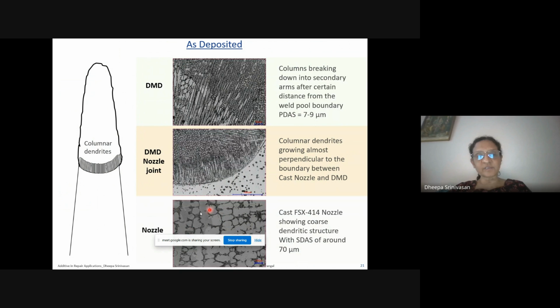What you could see here, the microstructure, this is the cast FSX414, and this is the additively manufactured powder based direct energy deposition. Except that here, as compared to the laser powder bed fusion, the columns are much larger, and there is a columnar or epitaxial growth, unlike in the laser powder bed fusion, where we said there was no texture at all. And you can see the primary dendrite arm spacing, the secondary dendritic arm spacing. You can see small dendritic features emanating out of the primary arms. So this has a very directional structure and quite different to that of the laser powder bed fusion. Of course, the material here is the material of construction of the vane that is used for the example in this particular case study.